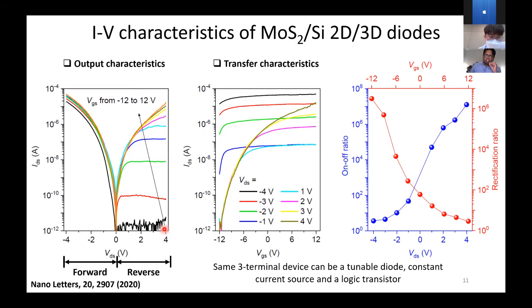But then when you reverse bias the diode and vary the gate voltage on top, you can change the reverse saturation current by orders of magnitude. As I was telling you before, this orders of magnitude change in current is mainly the tunneling current, right? And so if you put a drain bias over here and scan the gate bias, you'll get a very nice transistor property. But if you do it over here, you will get very little modulation of current, because here it's mostly diffusion current, and diffusion current cannot be modulated. So this acts more like a constant current source under forward bias.